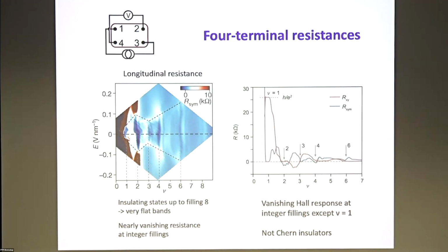There is an Rxx dip. But for all the other states like filling factor 2, 3, 4, 6, you can see all the way up to about 8 or even beyond that. It really shows that there are many, many states in this device because it's a very small twist angle. All the bands are really, really flat.